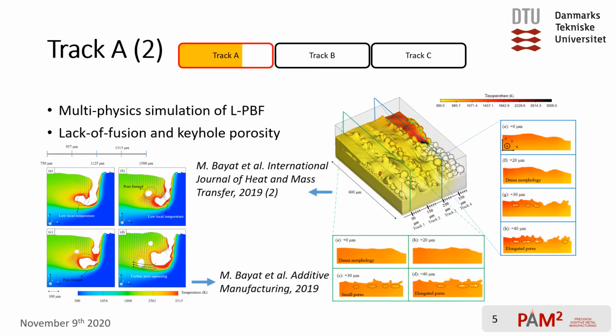In two other studies from the first investigation track, I developed multi-physics simulations of the LPBF process, where I managed to predict the formation and evolution of lack of fusion and keyhole porosity during the process. Then I compared the predictions of the model with the experimental data that I got from our partners from the PAM² project.